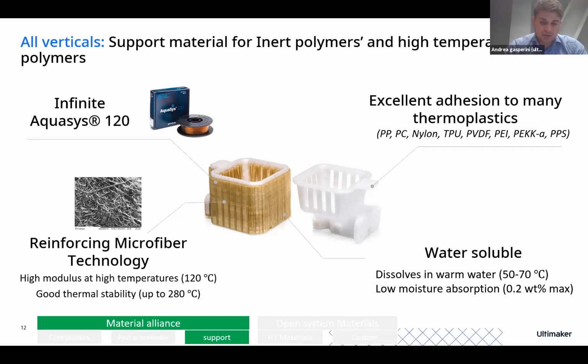So to have a contact with an extruded part is really based on a new motif, which is called the reinforcing microfiber technology that Infinite Material Solutions owns. And as well, it's a really easy to dissolve material, dissolving in warm water around 50 to 70 degrees without any need for a specific solvent or soap to be added. One key part of it is that differently from PVA, it has a really low moisture absorption, about 0.2 weight% maximum compared to the 10 weight% that normally PVA would have.